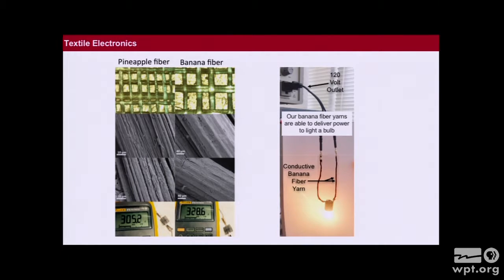So all of a sudden, just because of the PEDOT coating, we've actually made this textile conductive. And it's so conductive that if we coat a few fibers and make a little yarn of it, connect it to a light bulb, we can actually power a light bulb. So that's what this picture is, this black part. We're not really great photographers in my lab, but this black part is banana fibers that are passing enough current density to power a normal incandescent light bulb.